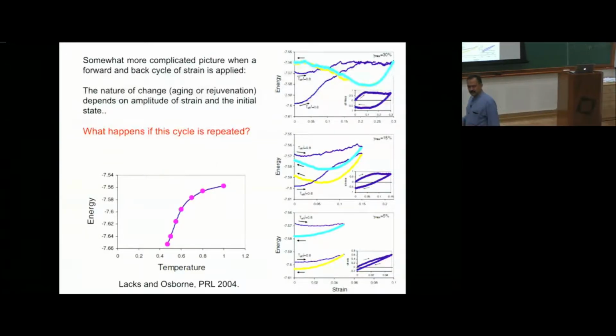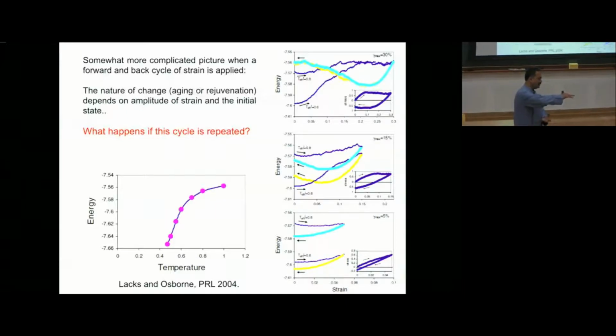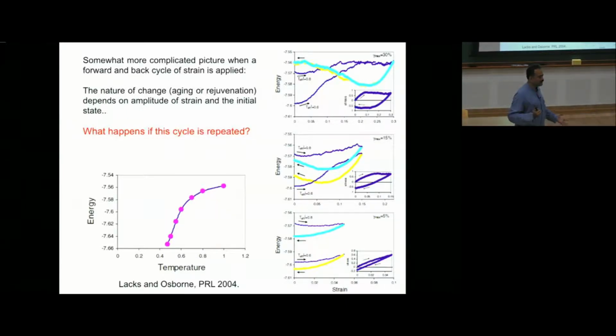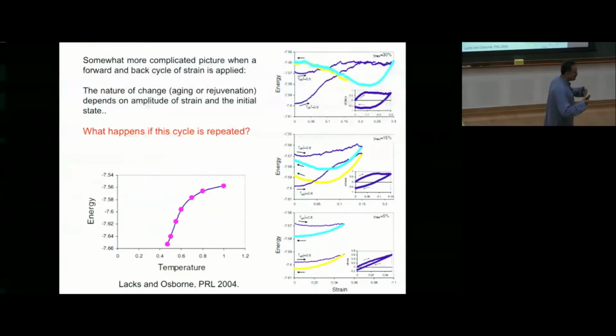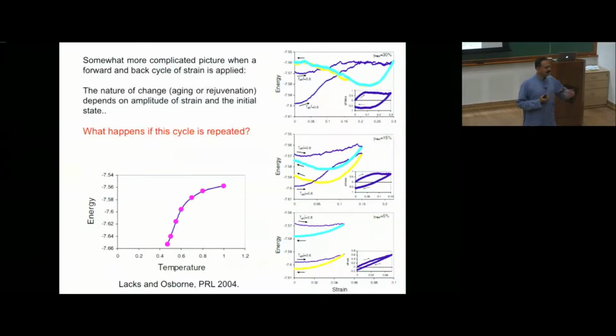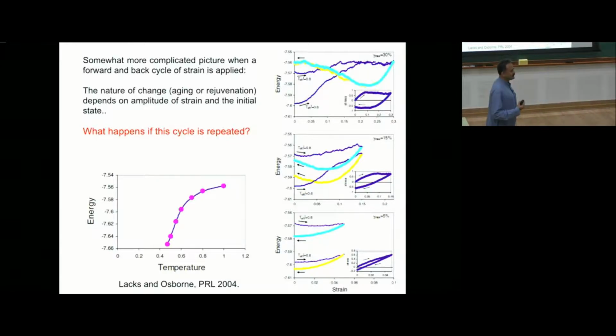So how do you decouple this elastic increase in the energy from some structural change that leads to increases in the energy? One thing you can think of doing is you strain the system up to a point, and then you strain back and ask where you ended up. This was done again many years ago by Lacks and Osborne, and what they found is that it's complicated, right? What you end up with depends on what your initial energy was, how far you pushed, etc., etc. But the interesting observation is that there are situations when the energy will decrease, right? And you can see that. The purple curves are the ramp up, and the cyan and yellow curves are when you come back. And you see that, in fact, there are regimes where the energy is actually going down.